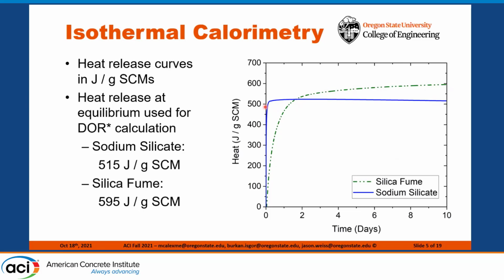The heat release happens so quickly that this line is composed of a couple of sets of data, with some data being from samples mixed inside the IC and others being mixed outside and then placed in after mixing. More research is needed on what's happening with internal mixing to verify these results, but we're pretty confident with these preliminary ones.